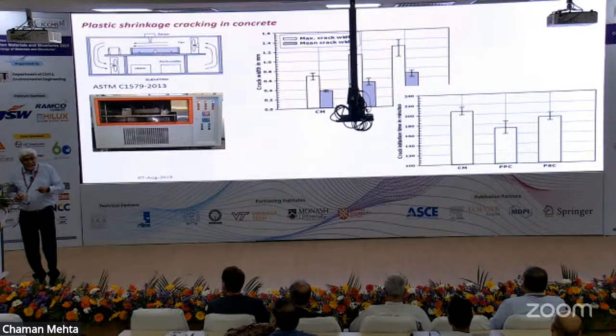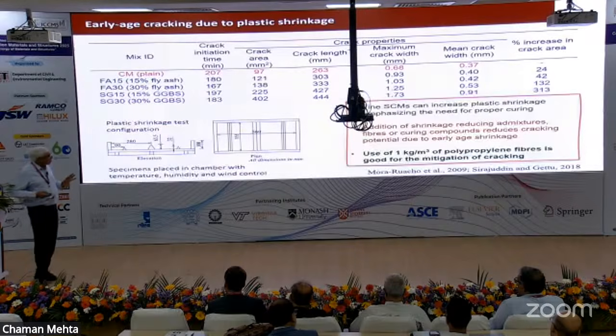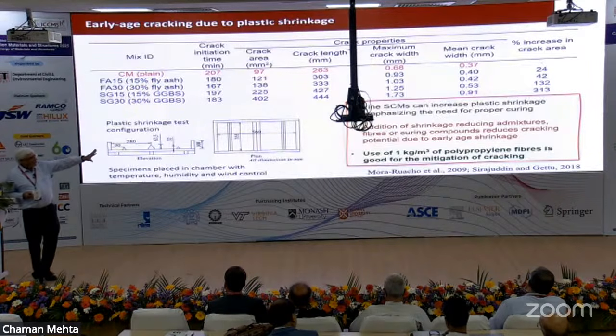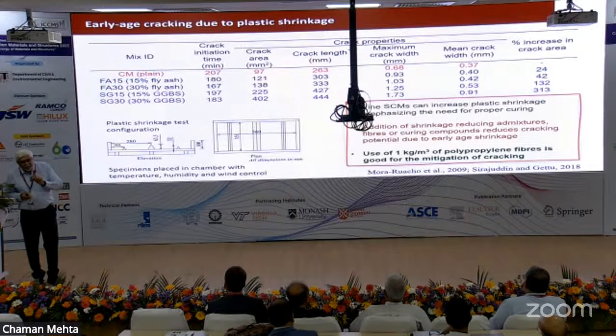Cracks are starting earlier. That means you have to cure fly ash concrete, slag concrete, LC3 concrete earlier and cure for longer. This is very, very important. We cannot relax and say that, okay, the concrete is taking care of itself. It will crack. Look at the numbers on your right, and you can see the increase in crack area. So we actually measured how much the crack area changes under these circumstances.